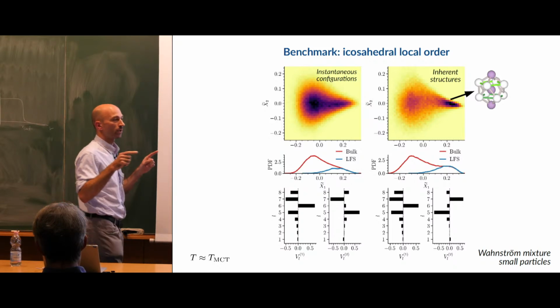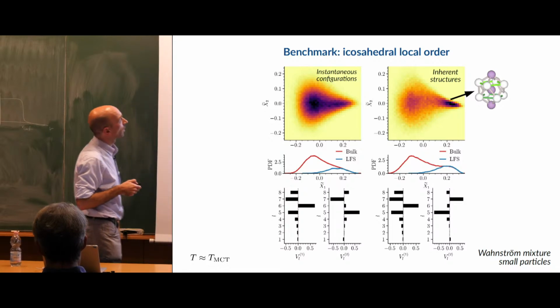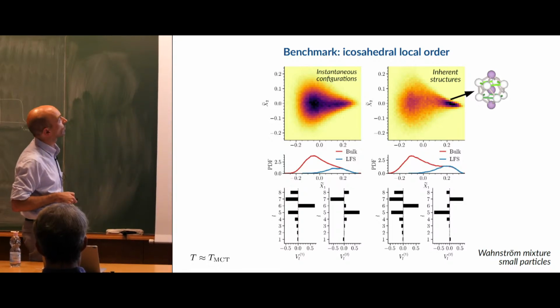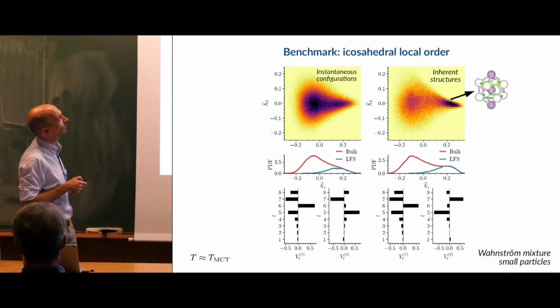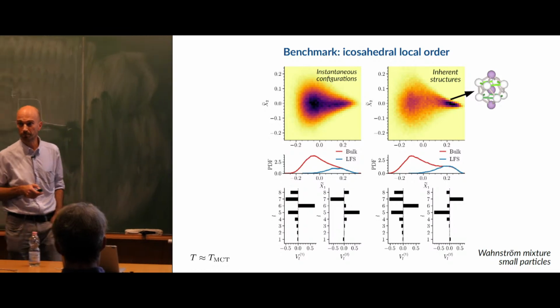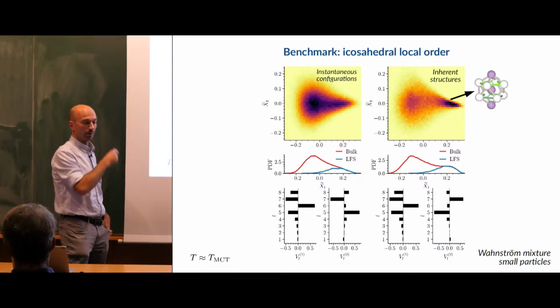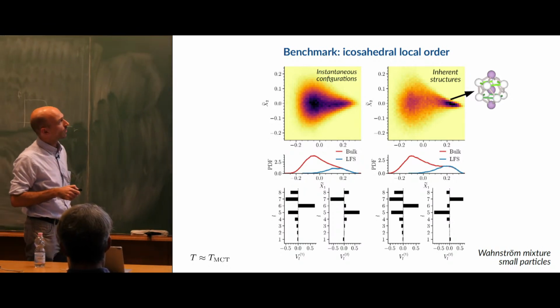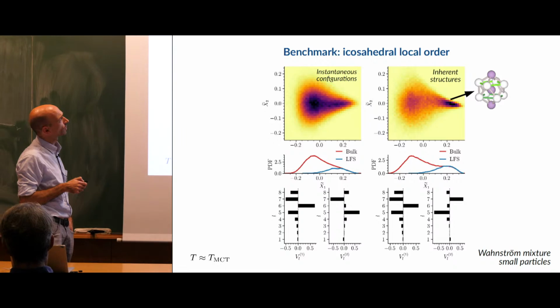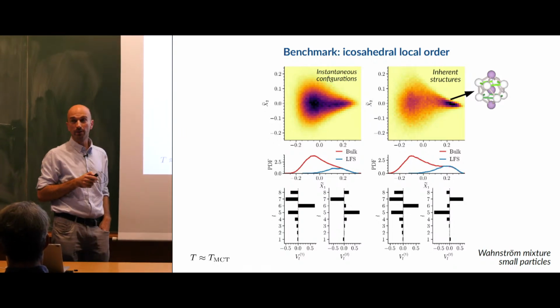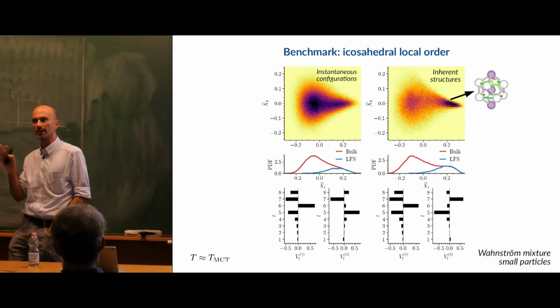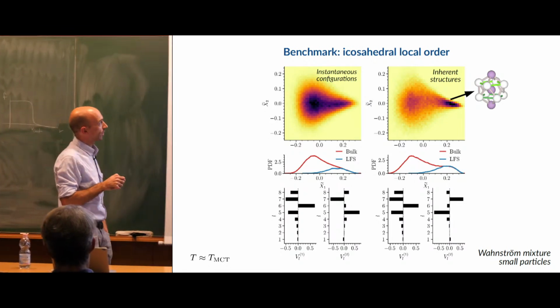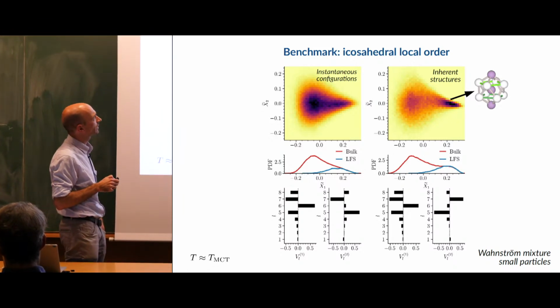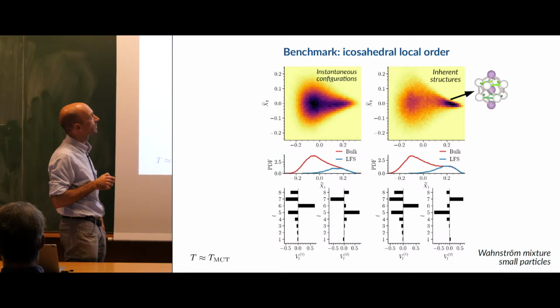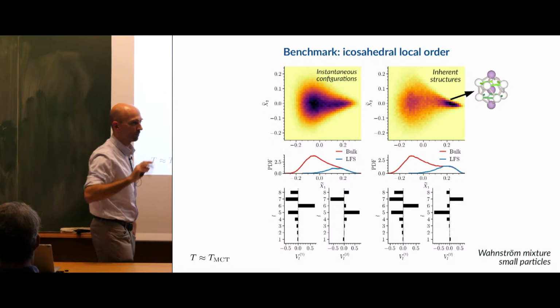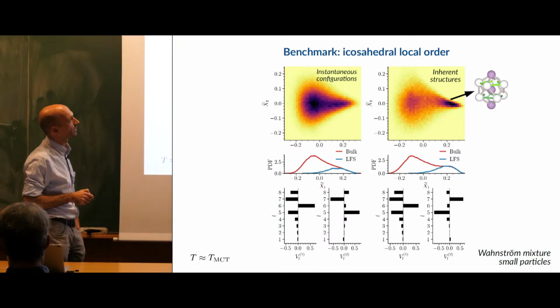And this is the probability distribution of those pairs, okay, for this system close to the mode coupling crossover temperature. Here it's instantaneous configurations, and here it's inherent structures. Okay. So this is the kind of map that also Gabor Csányi was looking at before. So one first thing is that if you look at inherent structures or instantaneous configurations, qualitatively the picture doesn't change. More or less we get the same kind of pictures, even though the balance of these 2 areas will be slightly different. So we can clearly recognize a central diffuse region here and a lobe that detaches clearly from the bulk. The same thing here, but this lobe is more populated.